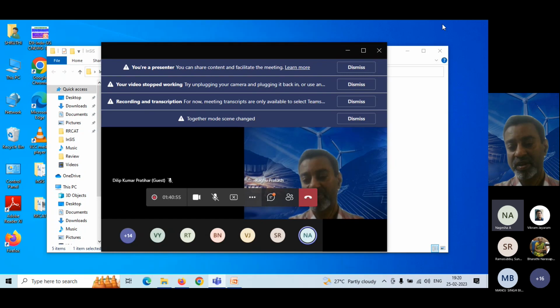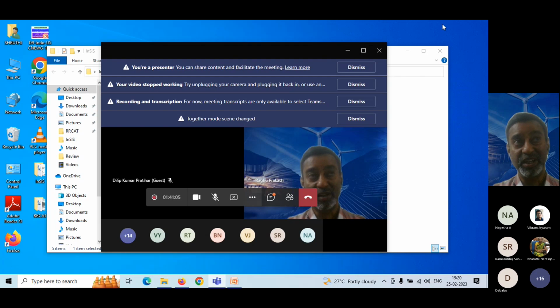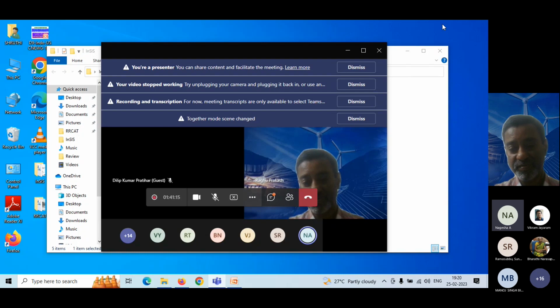Because many labs I know have purely air cooling systems, the heating rates are typically twice the cooling rates. Yeah, I see your point. It would be very important if you have much faster heating and cooling rates. In our case, the thermal cycling rate was about 2 to 3 degrees per second. If we go for 5 to 10 degrees per second, then there will be a problem.